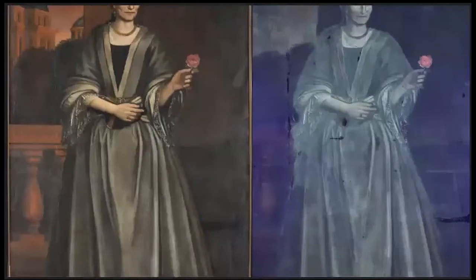Ultraviolet light allows us to examine the natural or synthetic resin varnishes that are applied to the surface of the paint film, their distribution, and overpaint that covers damage from previous restoration campaigns. In this example, we can see retouching along the seams in Arianza's canvas, pointing out areas of tears and punctures, which appear dark purple. The distribution of synthetic resin varnish and natural resin residues are uneven, suggesting that the painting has been selectively cleaned in the past.